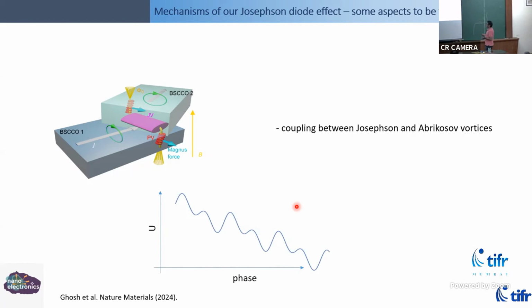Another way to think of the non-reciprocal response is that if you think of the current phase relationship of a Josephson junction, like I told you, if there are higher order terms in the Josephson current phase relationship, then switching from one side for one sign of tilting of this corrugated potential and tilting from the other side can be quite different. And that arises from the complexity of this current phase relationship, particularly if there is a time reversal symmetry broken state at the interface as those theorists predicted, it could give rise to this non-reciprocal response reflected in the current phase relationship. So that's the big picture.